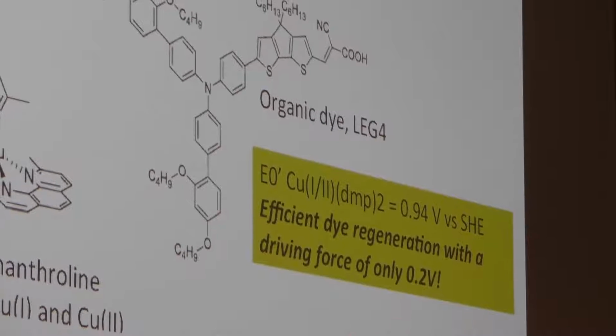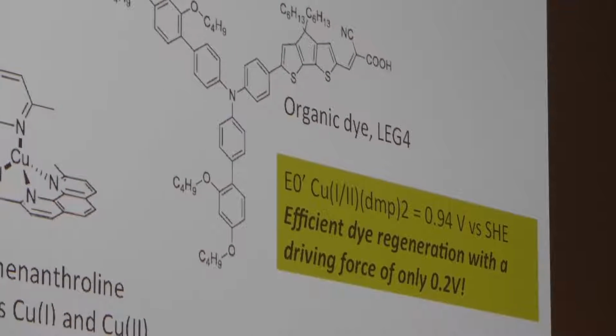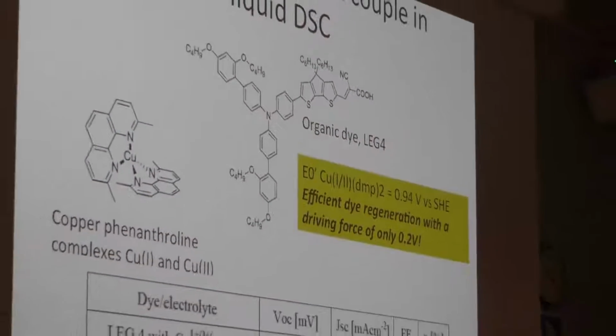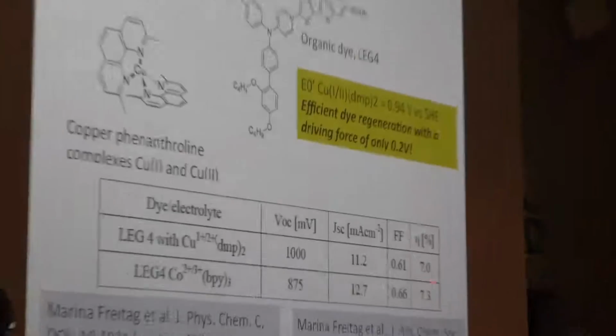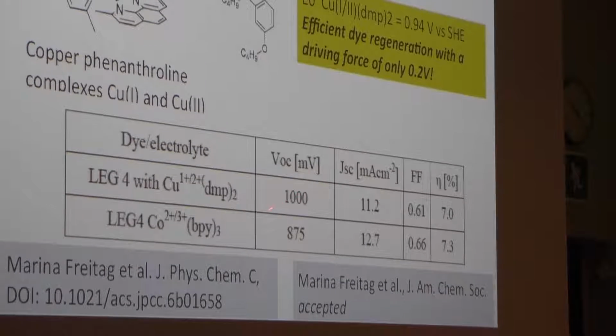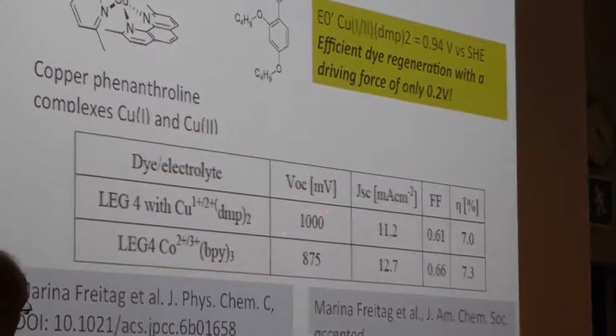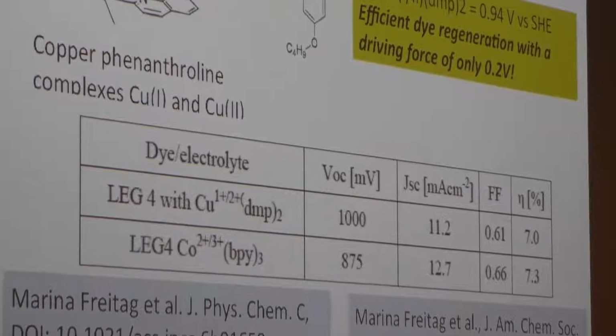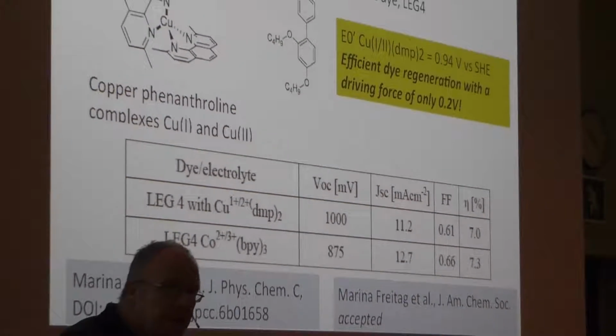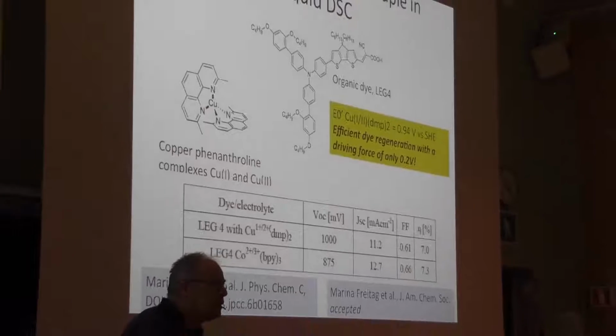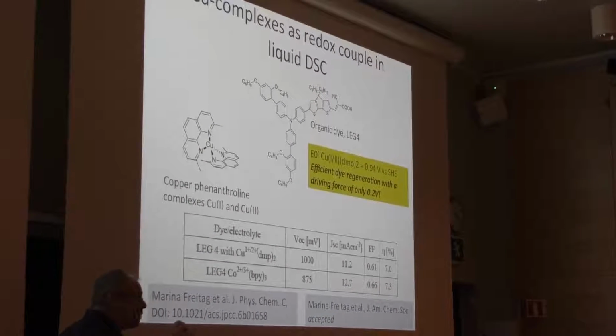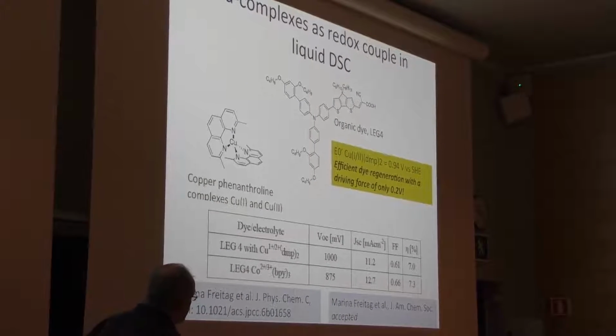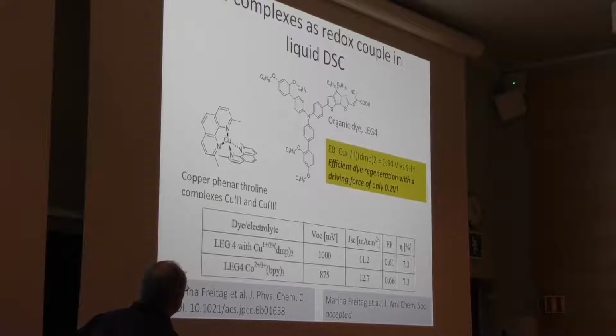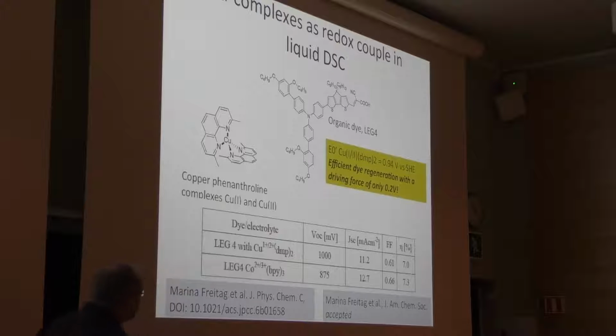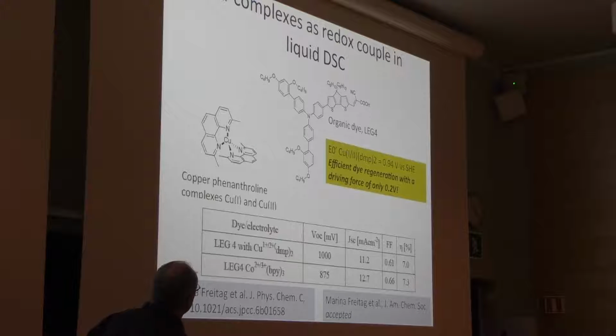Still it regenerates very efficiently, and the efficiencies in the first attempt we did were very similar between copper and cobalt as electrolyte. But the nice thing here with copper is that we have higher voltage, 1 volt here compared to 0.88 for cobalt. So we do have a redox system which regenerates very efficiently, but with the low driving force, and we can get the voltage out. So this is really what we are working on very much at the moment. We have the best results now, about 11% efficiency, with these copper complexes.